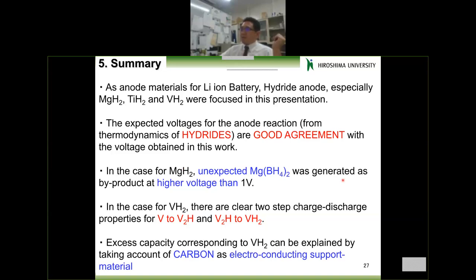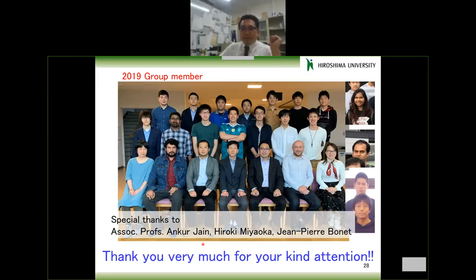And also in the case of vanadium, cycle properties are observed, but in this case, the carbon contribution is quite large for these electrochemical properties. And this excess capacity corresponding to vanadium hydride can be explained by taking account of this carbon as electroconductive supporting material. But this electroconductive supporting material itself does not show such a good result for charge discharge properties. So actually, some synergy effects are expected. Now we are interested in this phenomenon. Okay, thank you very much for your kind attention.